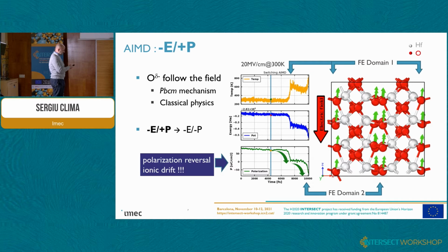Well, in any case, what you should see here is that the oxygen atoms are being driven by the electric field, and in this case they go up. First it goes the first domain, second it goes the second domain. We annihilate the total polarization first, and then the second domain gives us the polarization down. And then this is full switching of both domains.